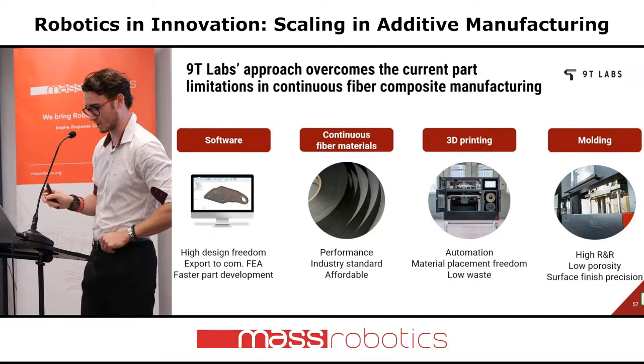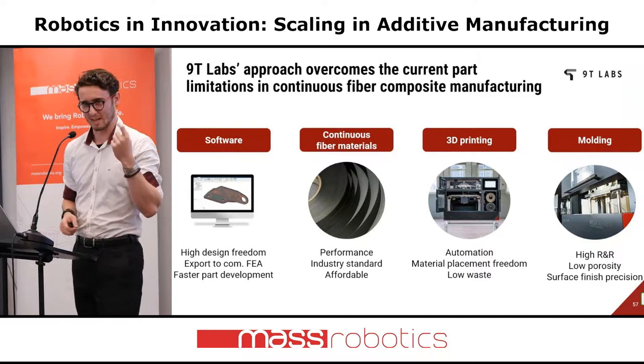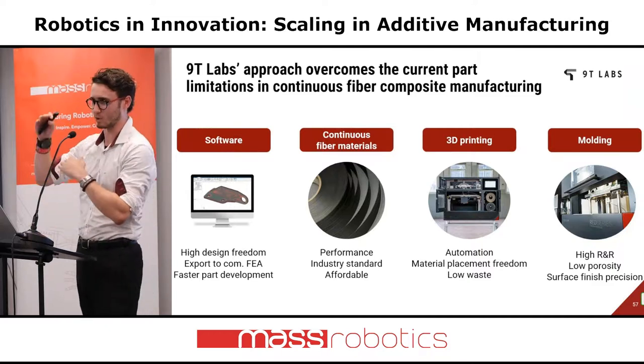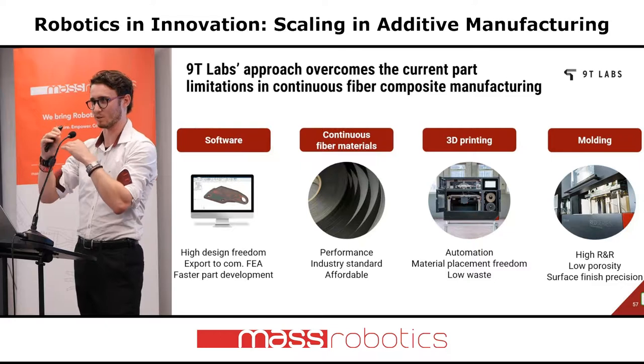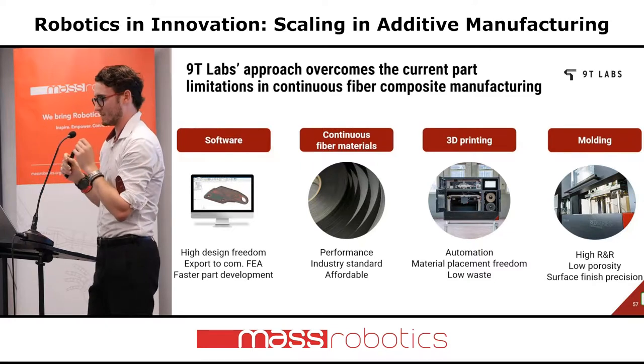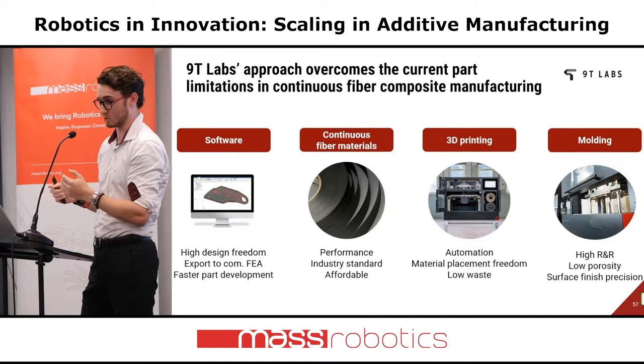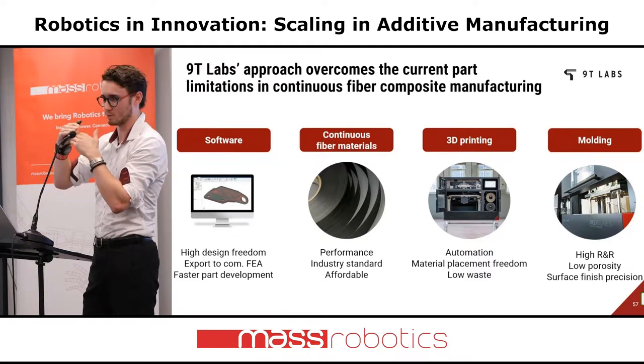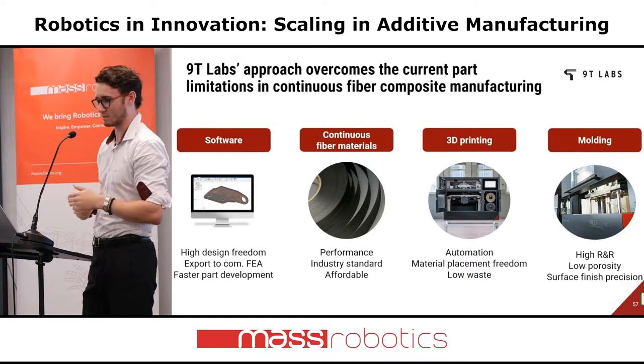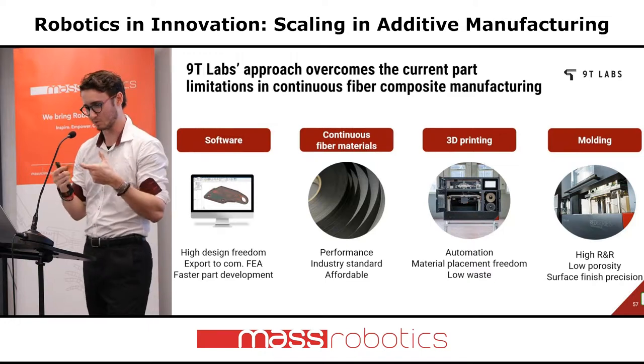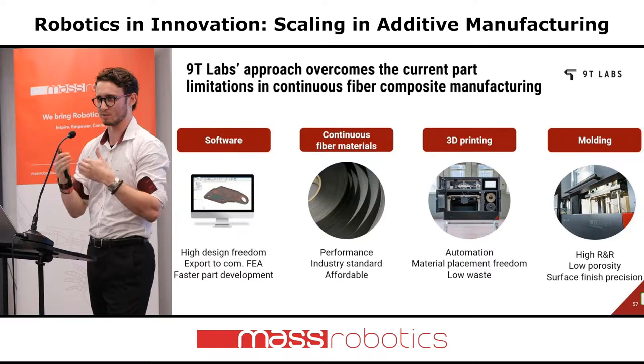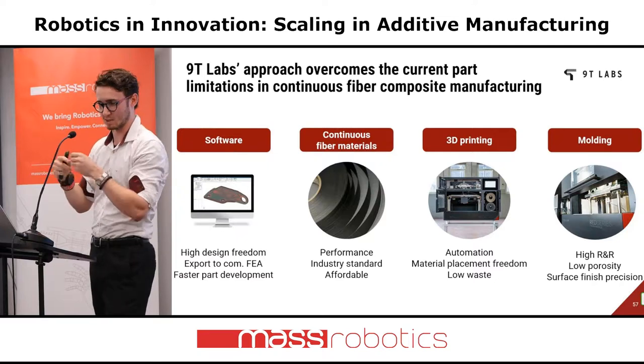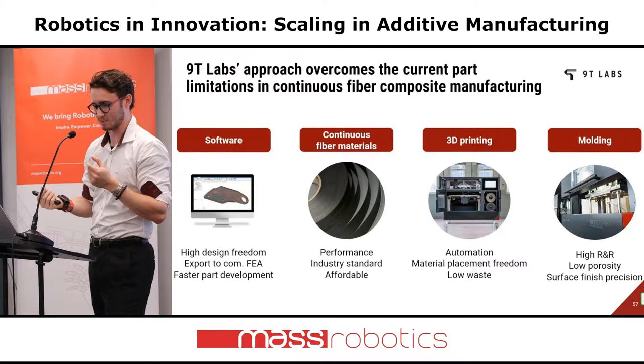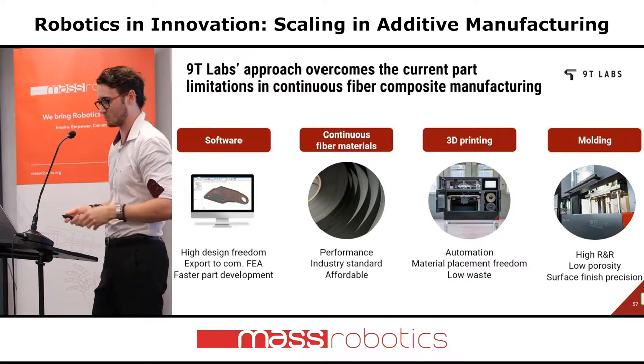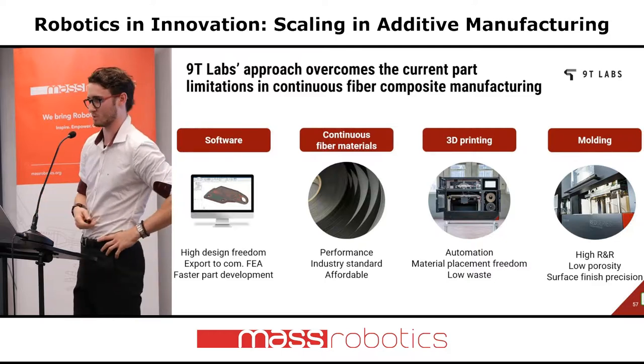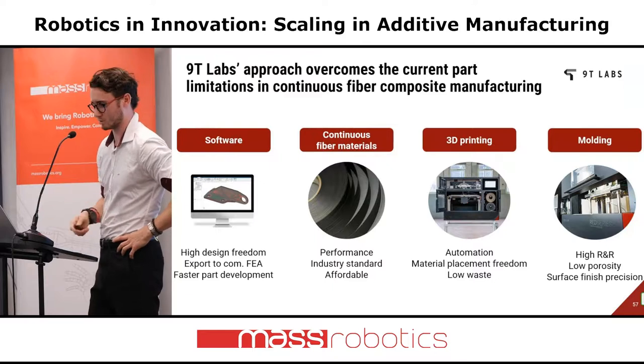And then the molding side, again, it's all about getting those surface finishes, especially with printing, getting rid of all those layer lines. And those layer lines, it's not really just a quality or appearance thing. It's really a mechanical issue. You have this low Z strength. Those layers can delaminate, as was mentioned, but even deeper into the microstructure of the part, there's the voids. I mean, there's voids between each printed bead, as they're called, or extrudate, and you really just can't have those. So for a structural part, those are all stress concentrations and points for crack propagation. So you really need to eliminate that.